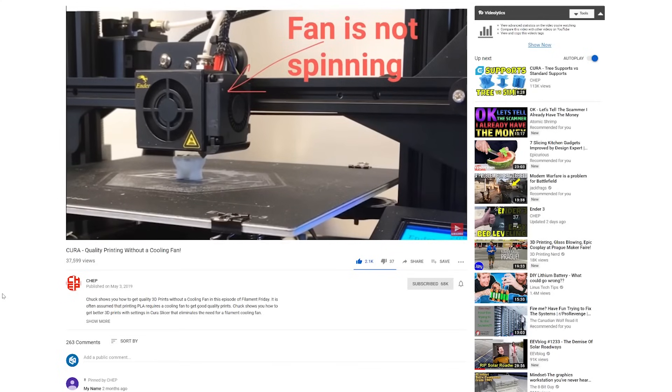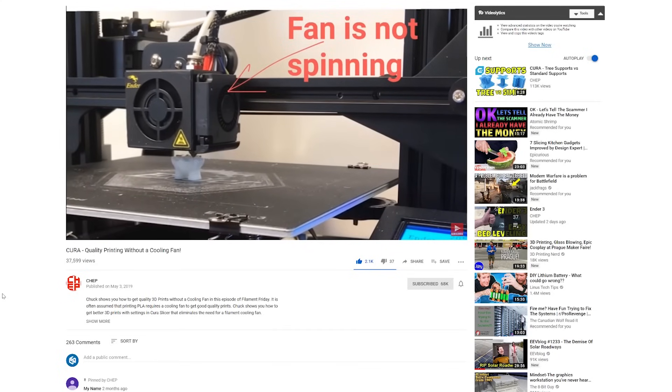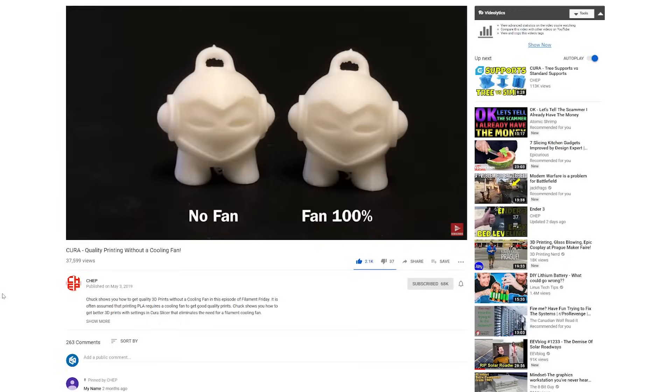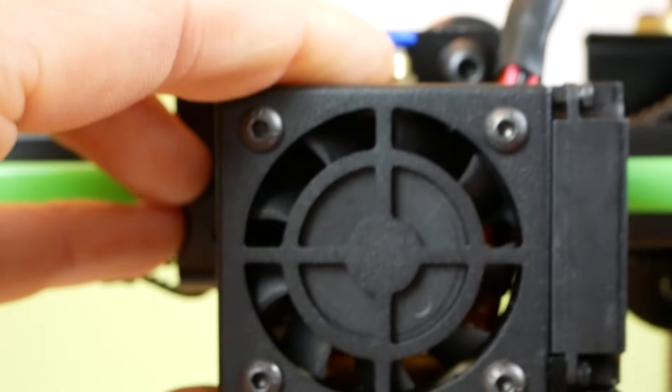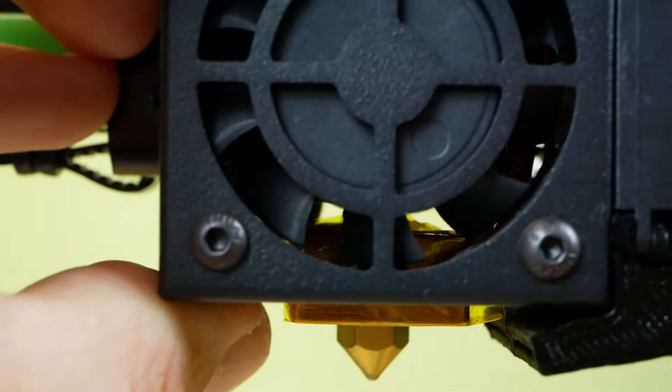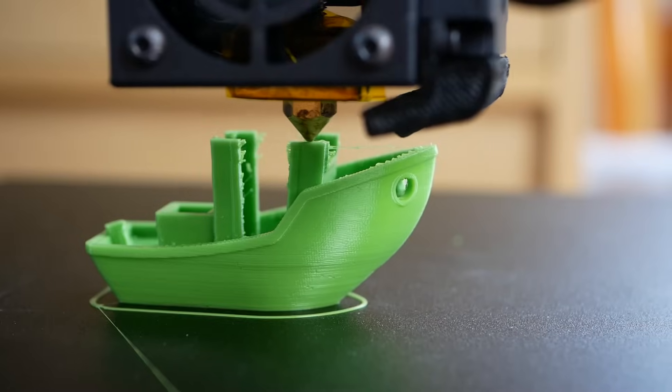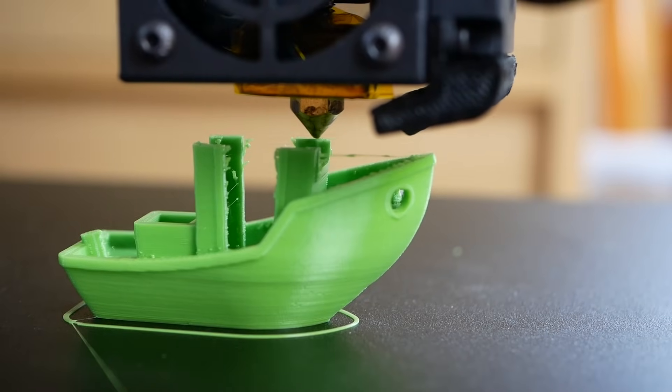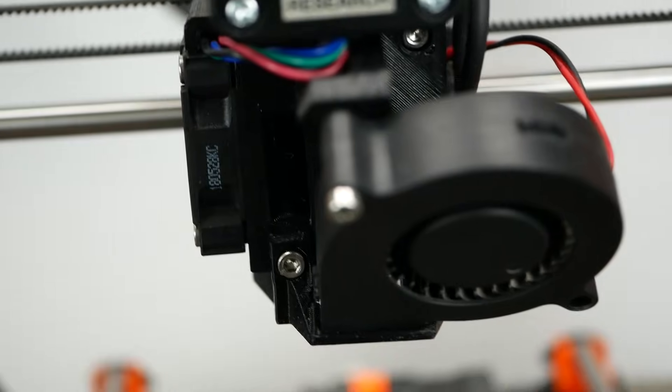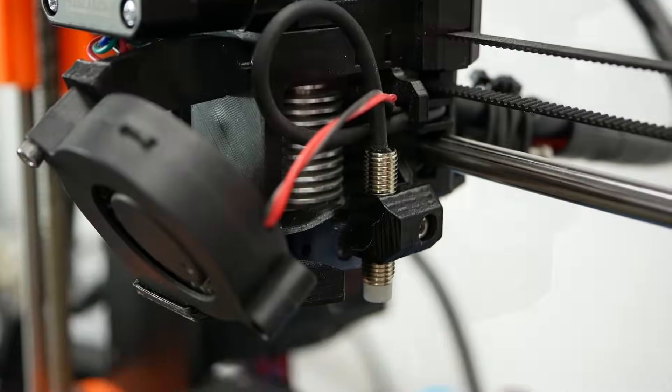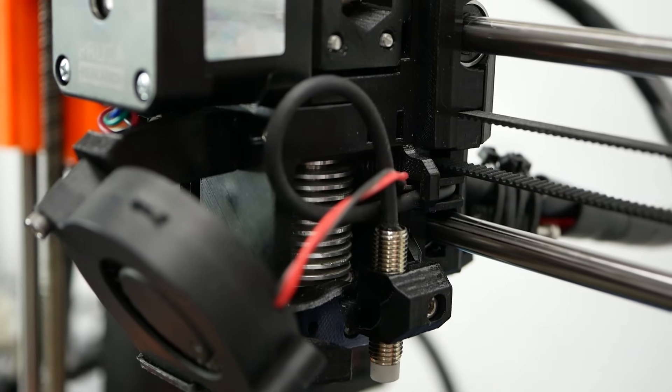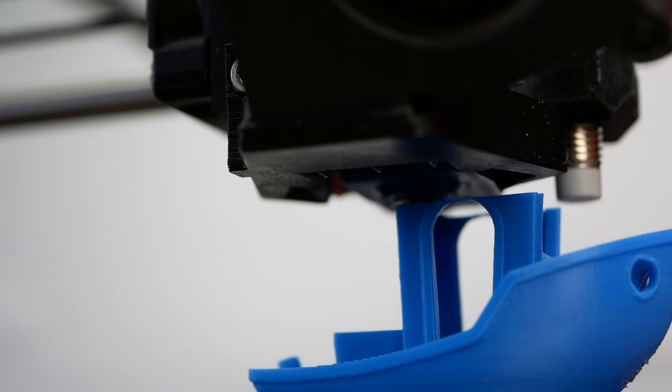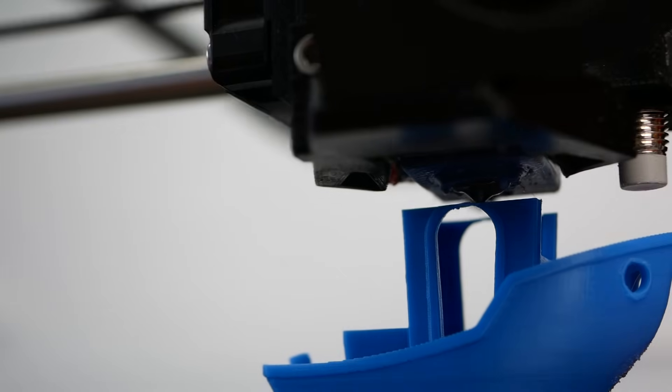Chuck from Filament Friday even stated that you can print PLA without any fan at all but he was using an Ender-3 for his tests. The thing is that all of the CR-10 variants have a horrible fan shroud design where the fan that cools the heatsink also directly cools your hotend and the print. So 0% on such a machine is still some cooling and will decrease layer adhesion. The Prusa on the other hand has two totally separate cooling paths where no cooling air from the heatsink touches the print and therefore 0 part cooling fan also means no cooling at all. That's also quite important for the higher technical materials like nylon, PC or even ABS. Just keep that in mind.